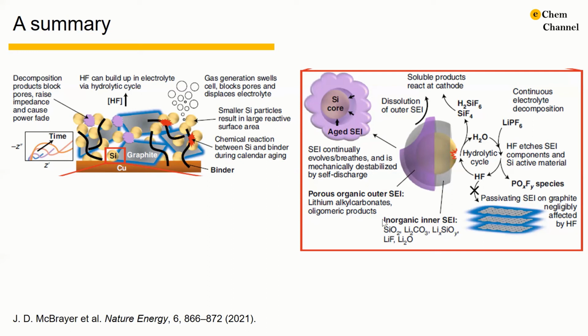Although the inorganic inner SEI is relatively stable, the outer organic SEI is reactive and soluble. This causes the breathing effects, leading to continuous electrolyte consumption and pore obstruction. Since the SEI experiences constant morphological and compositional change, its ability to protect the silicon core is also affected. Also, due to the continuous consumption of the electrolyte, sustained loss of lithium-ion inventory is expected in silicon-containing anode as well, which also limits the calendar aging of the silicon-containing cells.